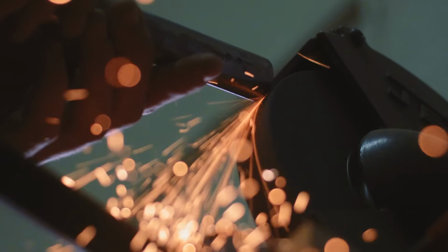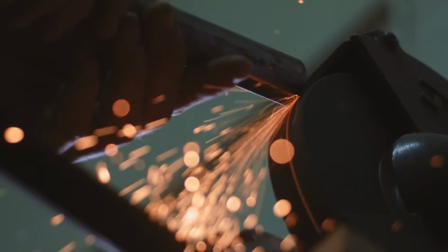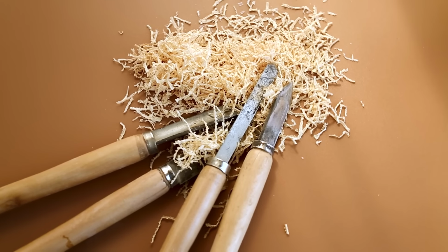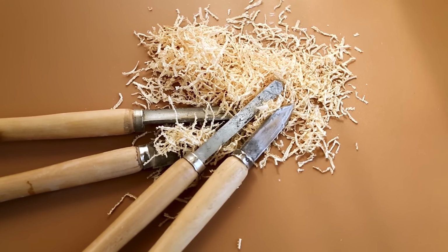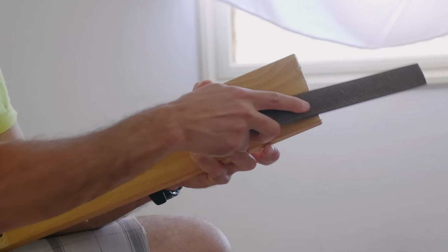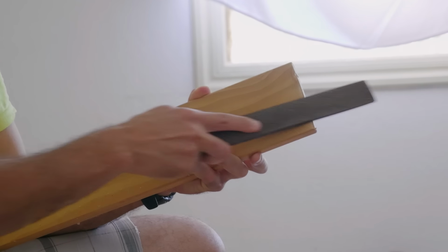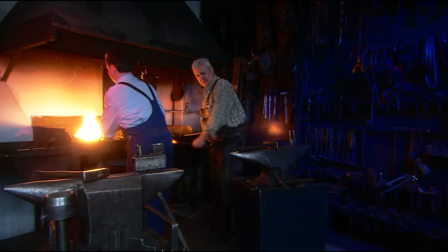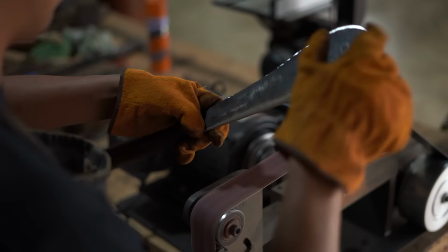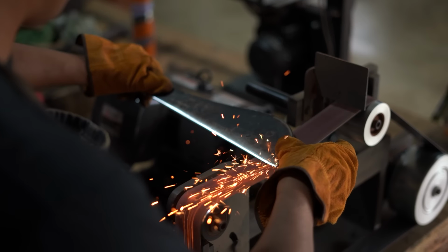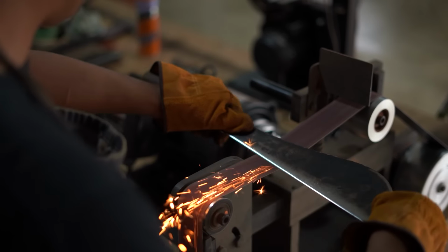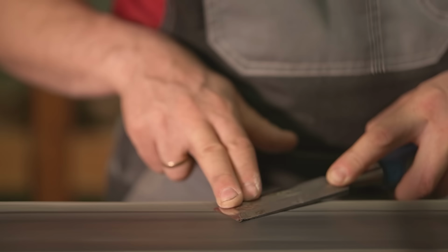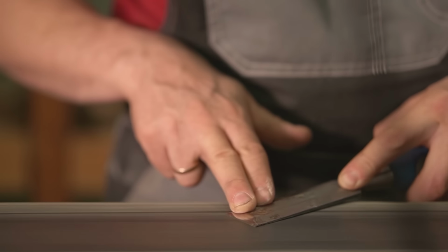Most often, this means grinding with a stone to reshape and recreate the cutting edge. But remember, the hard layer is whisper thin, so as soon as you do that, you could be down to soft metal. That's why this technique works best for either very thin pieces, where you can get the carbon down into the core, or tools like files, which don't tend to get resharpened. If you're in the habit of buying old files or rasps and that sort of thing to forge into new items, sometimes you run into this problem, where what you thought was a nice piece of tool steel is actually just case-hardened iron. So when you reshape it, suddenly it won't hold an edge anymore.